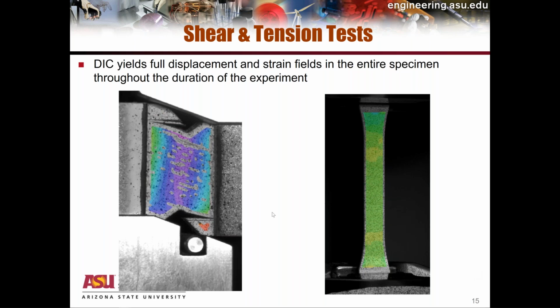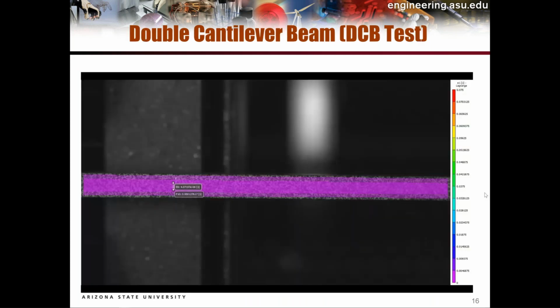And on the left, the shear test is stopped when we run out of room in the test equipment to carry the test further. And on the right, we get a very nice crack in the gauge section in the center of the specimen. So we have reasonably good, reliable data available to us to build our constitutive models.